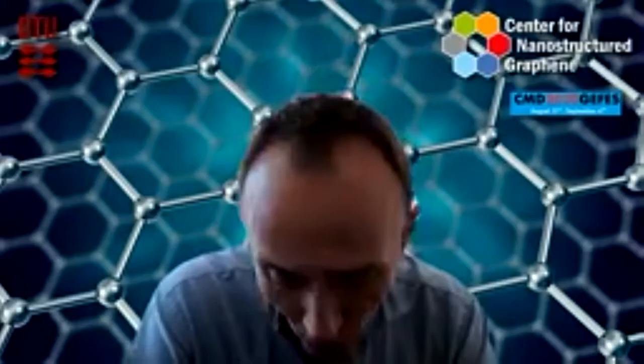The thing is that when you make an oxygen-based etch, you nearly always end with oxygen on the edges. And when you do a fluorine-based etch, you end with fluorine. That's why, because most groups use a fluorine etch. So that means that they haven't seen this hysteresis, because the fluorine eliminates it. The water molecules can't bind to the fluorine. It's like it has Teflon on the side.